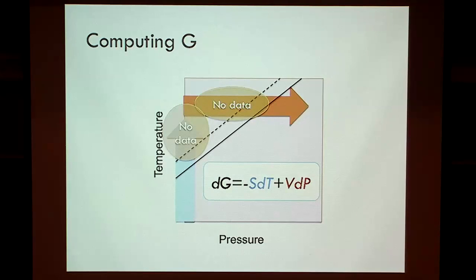Okay. So if we're thinking about forsterite, say, or magnesium silicate perovskite for applications to the deep Earth, you want to go up to 100 GPa and 4,000 Kelvin, right, in principle? So going up at 1 bar to 4,000 Kelvin, you're going way above the melting curve. Okay, so you can't actually measure the properties of perovskite along most of this integration path because it's melted long ago and it's become elastically unstable, possibly.